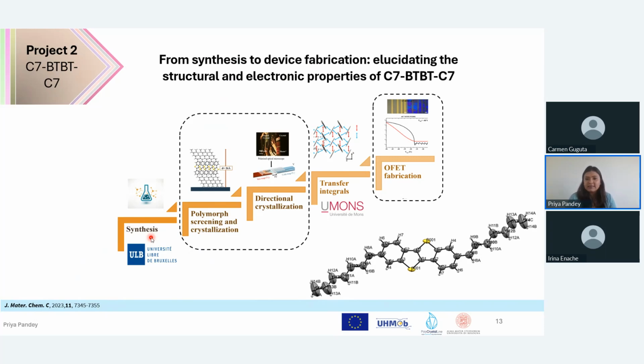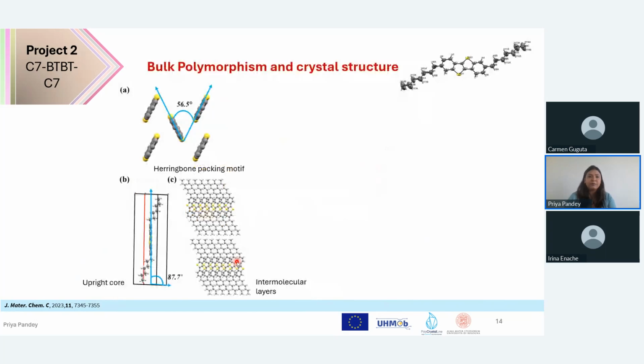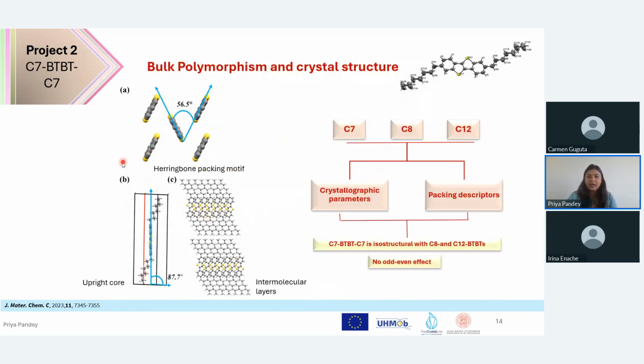So I have selected this C7BTBT. Basically, it is a 7 carbon atom long alkyl chain that is functionalized at 2 and 7 positions. From the bulk polymorph screening, with all the different methods we have tried, I could only find one crystal form. And comparing the crystallographic and packing parameters of C7 with that of the published C8 and C12, we found that C7 is isostructural with both these molecules, and there is no such odd-even effect that we can see.